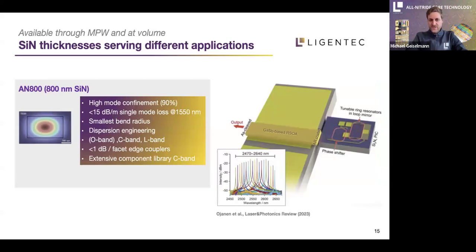And as you have a very high mode confinement for the C band, you can even go higher in wavelength and also propagate wavelengths in the regions of 2.5 micron, which has been shown in this work where a laser was attached to a silicon nitride circuit, and where they could tune the laser and narrow the line width even at 2.5 micron of wavelength.